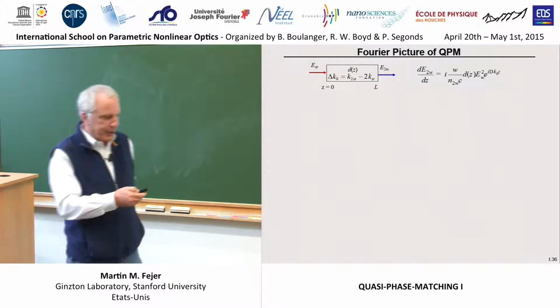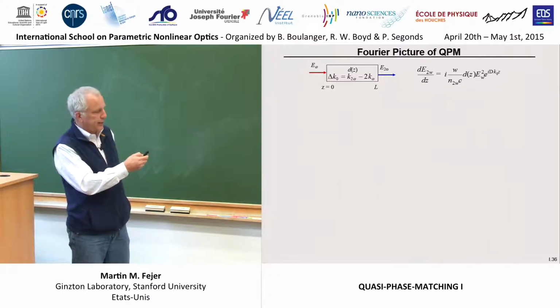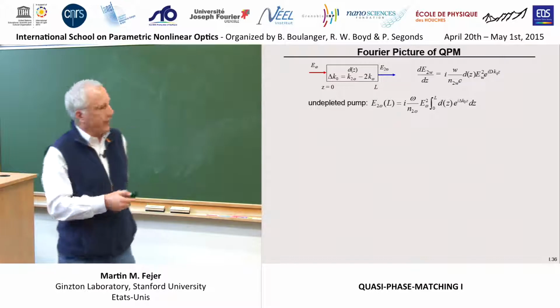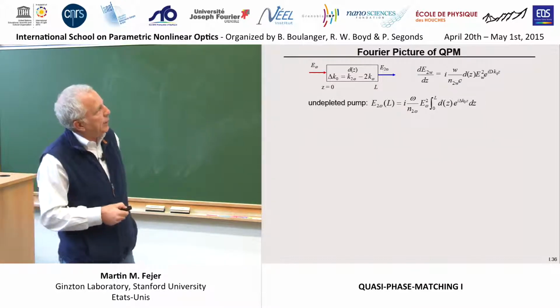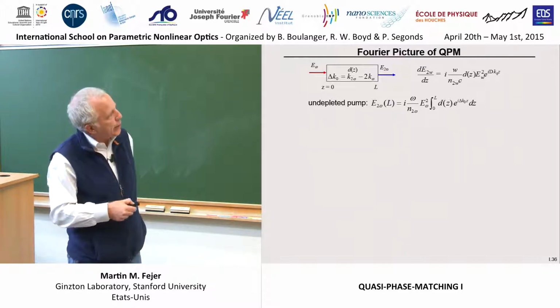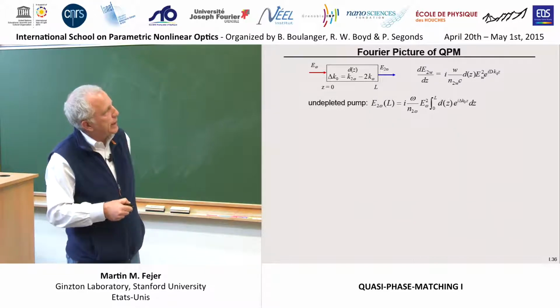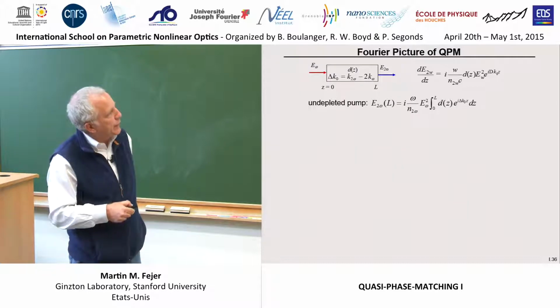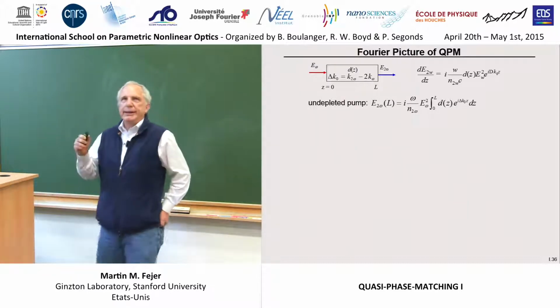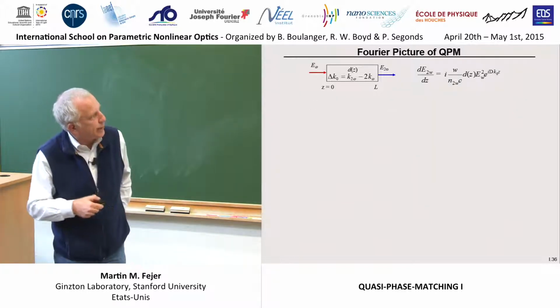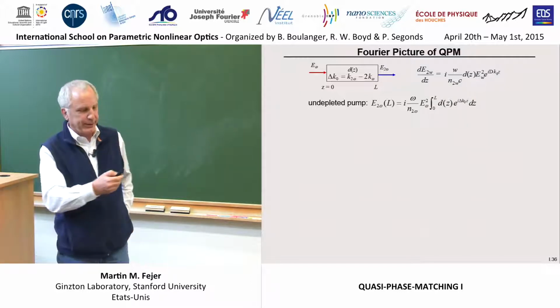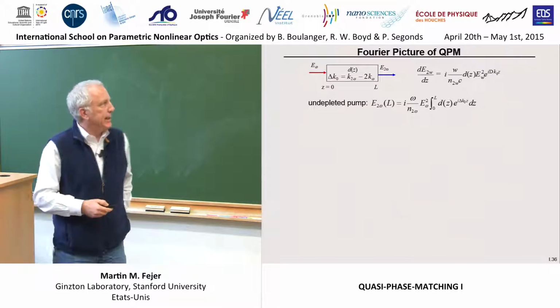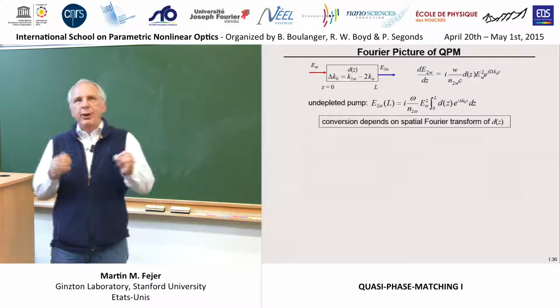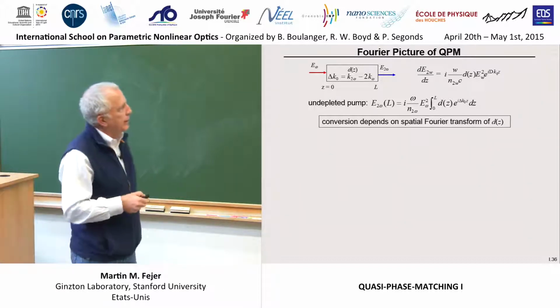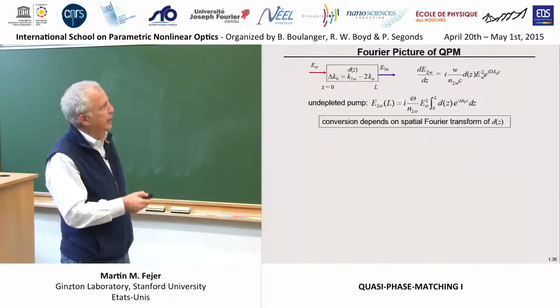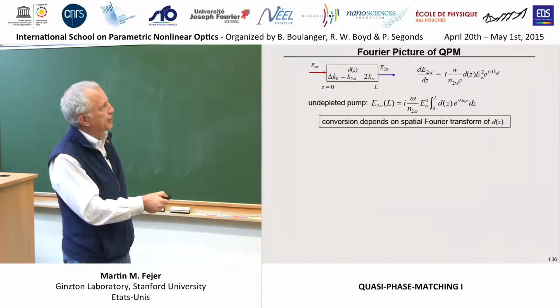And the phase mismatch, e to the i delta k z, is just the difference between the k vectors of the interacting waves. So if the pump is undepleted so that we can treat it as a constant, we can integrate this evolution equation, and we see that the generated second harmonic at the output of the crystal depends on the integral over the length of the crystal of the nonlinear coefficient times that phase mismatch factor. This probably looks to you like the Fourier transform of a nonlinear coefficient distribution, with spatial frequency delta k. And in fact, that's true. The nonlinear frequency conversion depends on the Fourier coefficient of the nonlinear susceptibility at the spatial frequency equal to the phase mismatch delta k.